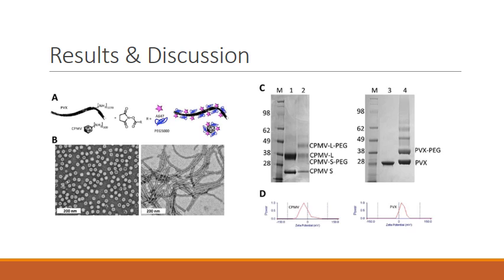Both of the nanoparticles were pegylated to prevent immunogenicity, decrease nonspecific interactions, and increase circulation time in plasma. This first image shows the characterization of the two particles, indicating the molecular weight and zeta potentials. In order to view the particles, Shukla et al. attached a fluorescent moiety onto the viral nanoparticles. This is also done in subsequent assays in this study.